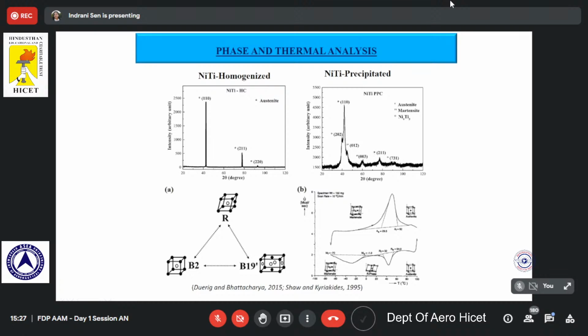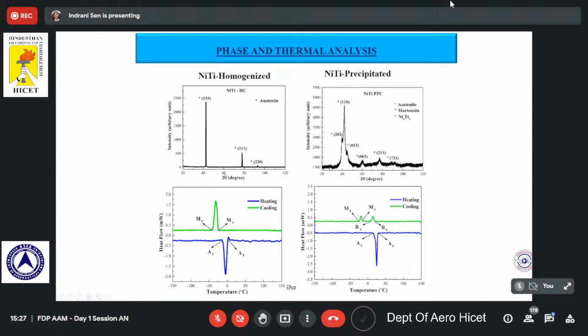So let's see what it does to the thermal treatment behavior. Because of the presence of these precipitates, the phase transformation from B2 to B19 can happen. So this is what we have seen. For the case of homogenized one, we see a typical austenite and martensite structure conversion, as we have seen, that the austenite finish temperature is only 3 degrees centigrade, so much below the room temperature.